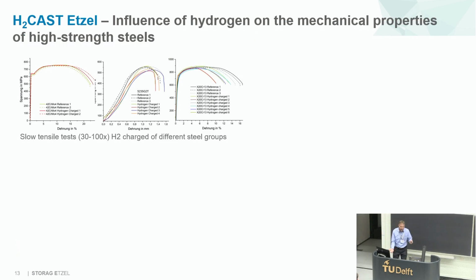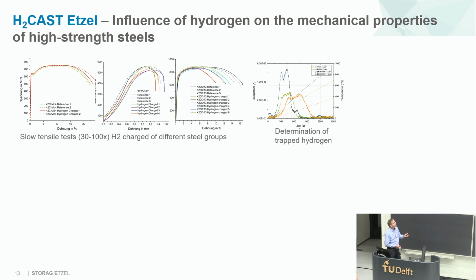And in parallel, we did a lot of material investigation. Another university with material science did this for us, and the results are quite easy. For the lower carbon steels there isn't any question, but we tested the higher carbon steels. For example, for the packers and the safety valve, we have some high strength yield steels, and they could have an impact from hydrogen influence. We also tested the maximum load of hydrogen in the steel, because you can only have a hydrogen-enforced embrittlement risk if the hydrogen gets into the structure of the steel. And there were some very interesting results.